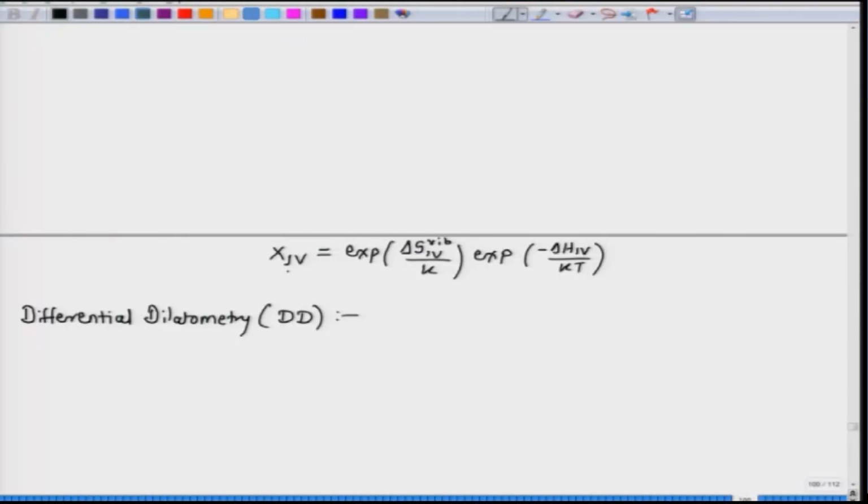As we have seen, the vacancy concentration varies exponentially with temperature, which is clear from this equation. As the temperature increases, vacancy concentration increases exponentially, and the way the vacancies are formed, which we have seen last class, introduction of a vacancy gives rise to one additional lattice site into the crystal. And so, as the temperature increases, to maintain the equilibrium, extra vacancies are formed, and so the extra lattice sites are added to the crystal structure.